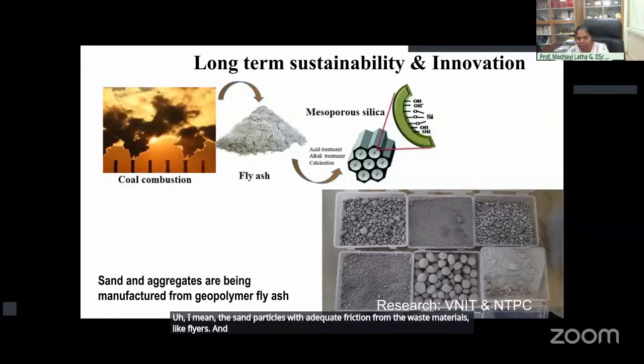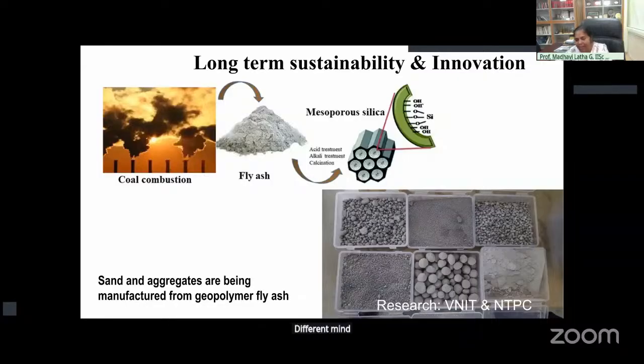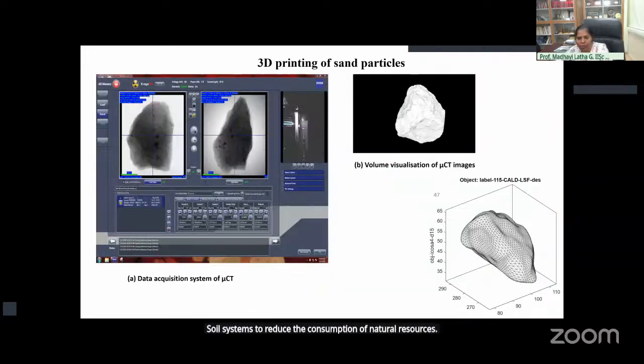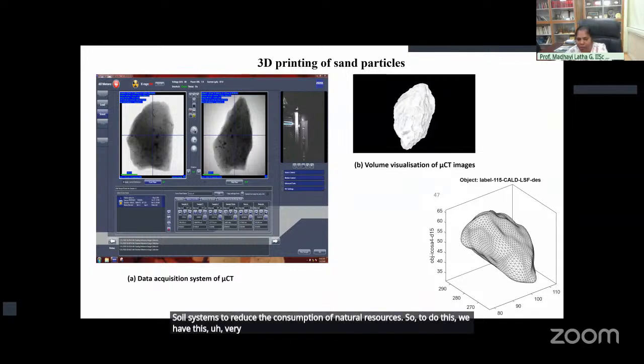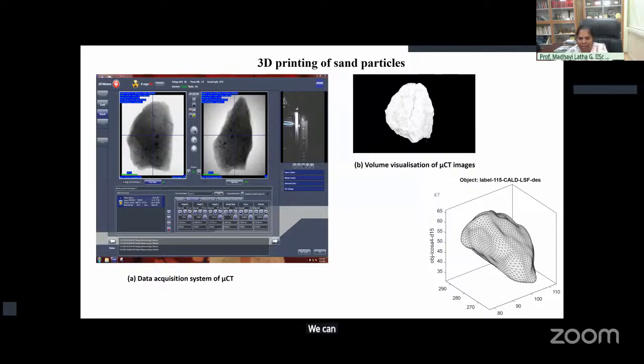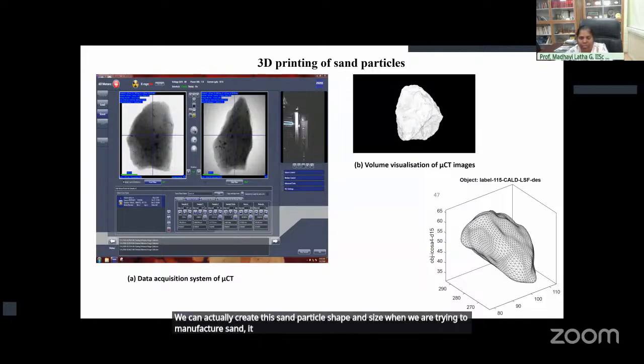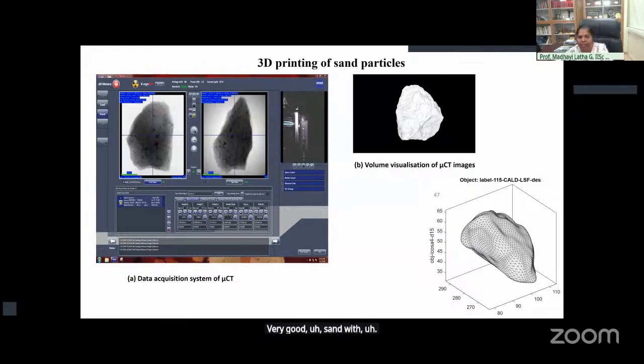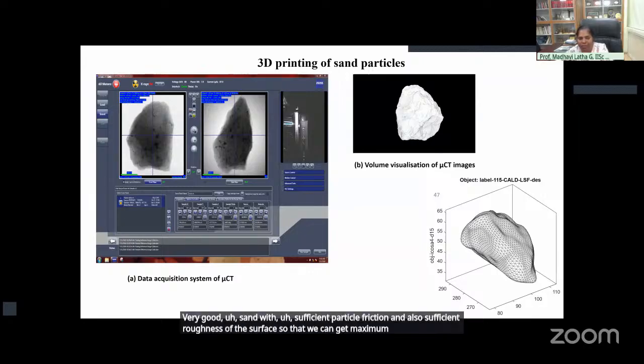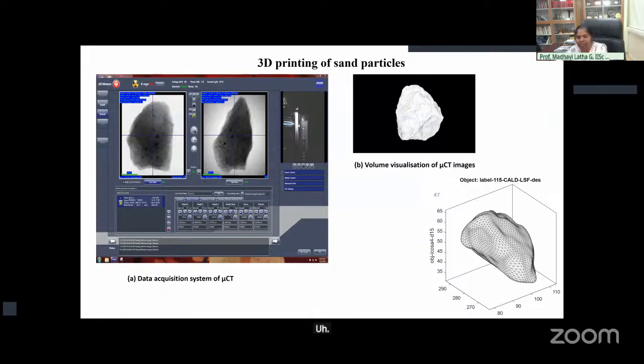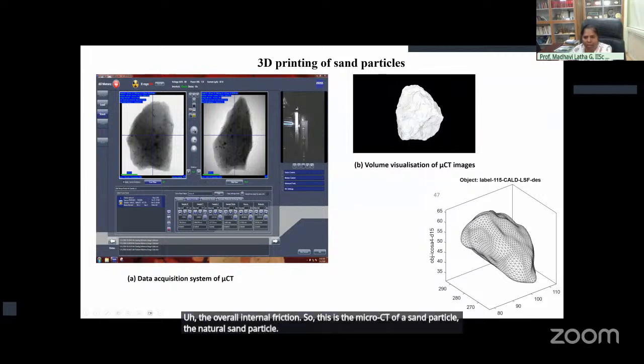And at our lab also, we're doing a lot of research on different mine tailings, how we can convert them or potentially use them along with our reinforced soil systems to reduce the consumption of natural resources. So to do this, we have this very fine micro level research going on where we can actually create this sand particle shape and size. When we are trying to manufacture sand, it's as well a very good sand with sufficient particle friction and also sufficient roughness of the surface so that we can get maximum benefits out of interfacial friction and the overall internal friction.